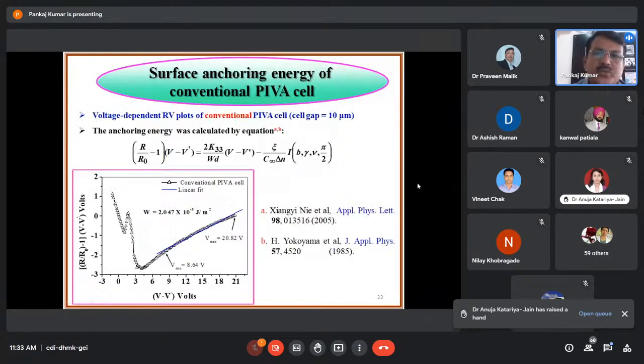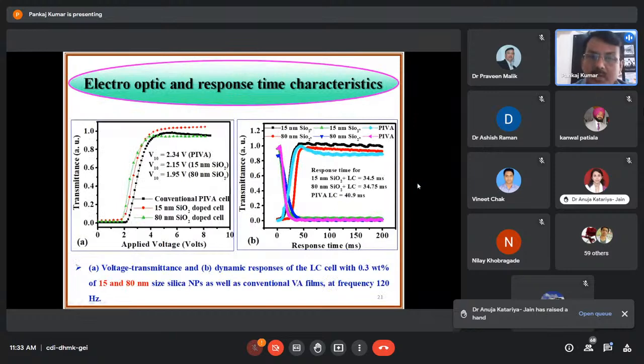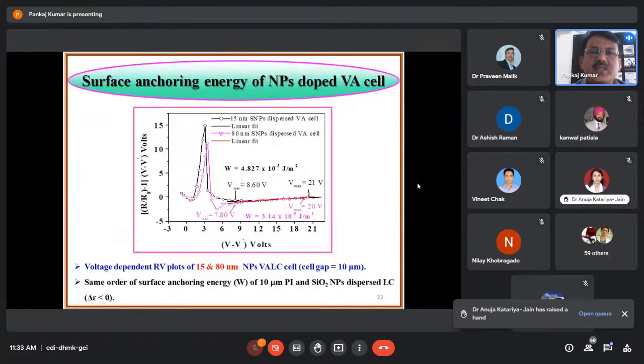The response time is fast. The operating voltage is very low as compared to PIVA cells. So these characteristics make nanoparticle dispersed display cells much more, I would like to say, applicable for display devices as compared to commercially used polyimide or some other methods which are very sophisticated, which cannot be performed in each and every lab.